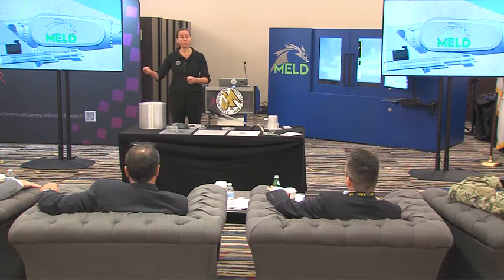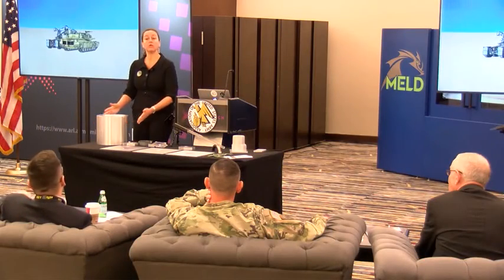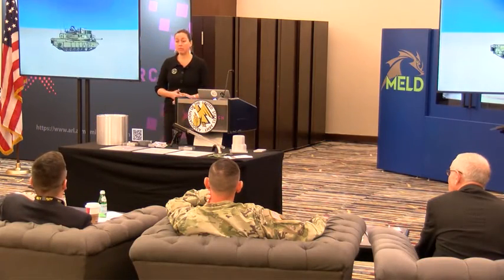Cold spray has a lot of flexibility. It's basically wherever you could take a garden hose to, you could take the cold spray solution to, but it does still see voids and porosity at the interface, as well as the added material, and it's not a technology that you would build parts with. I think it's an excellent repair technology.